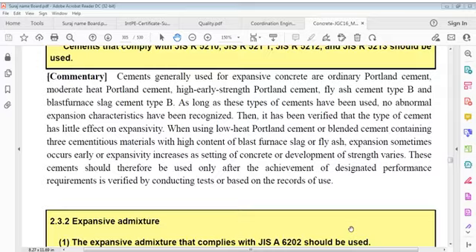As long as these types of cements have been used, no abnormal expansion characteristics have been recognized. It has been verified that type of cement has little effect on expansivity. When using low heat Portland cement or blended cement containing three cementitious materials with high content of blast furnace slag or fly ash, expansion sometimes occurs early or expansivity increases as setting of concrete or development of strength varies. Cement should therefore be used only after achievement of designated